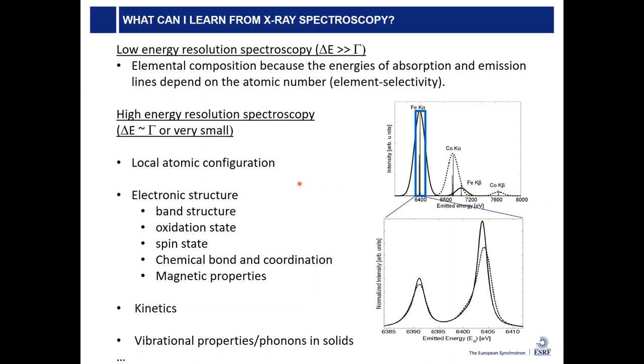But we would like to learn more, so we need high energy resolution spectroscopy, where the instrumental broadening is on the order of the core hole lifetime broadening, or even much smaller, in the milli-electron volt range. And this is shown here. If you have this better resolution, using crystal analyzers, for example, at a beamline, you resolve the fine structure of, in this case, the iron K-alpha line. And in this case, there are two different spin states of the iron in the sample, and you see there's a chemical sensitivity. So the high spin system here in the dashed line has a different shape, a broader K-alpha line than the low spin system. So if you do it with higher resolution, suddenly you see the chemical dependence in the X-ray emission line.